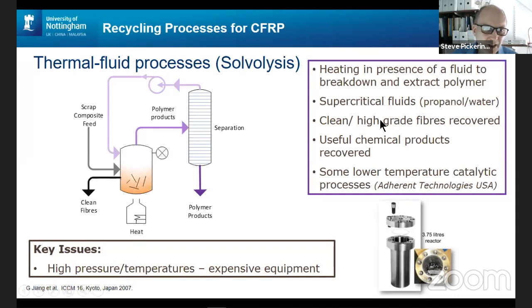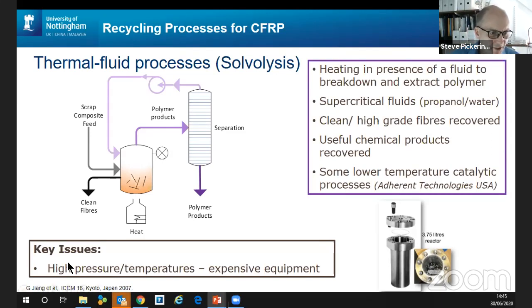Generally, you'd start the process off at fairly high temperatures, and you thermally degrade the polymers to begin with, before the supercritical fluids or other fluids would dissolve out the polymer. But there are some lower temperature catalytic processes that have been proposed, and Adherent Technologies in the USA are one company that have proposed that. I think the key issue here is that, particularly if you're using supercritical fluids, that needs very high temperatures and pressures, and high pressures mean expensive equipment, so there's a capital cost challenge there.